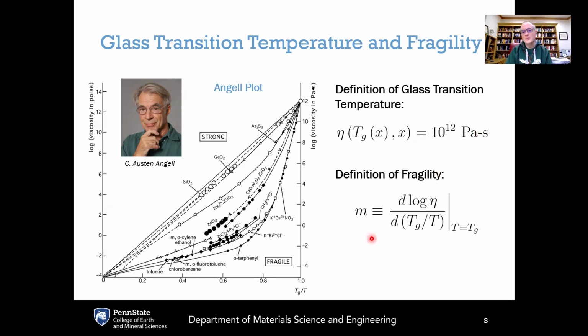The other key parameter is the fragility, and this is quantified by the fragility index M. And this fragility index is just the slope of this Angell plot at the glass transition temperature. A steeper slope here means a higher fragility. That means that the viscosity is changing more rapidly with changes in temperature.